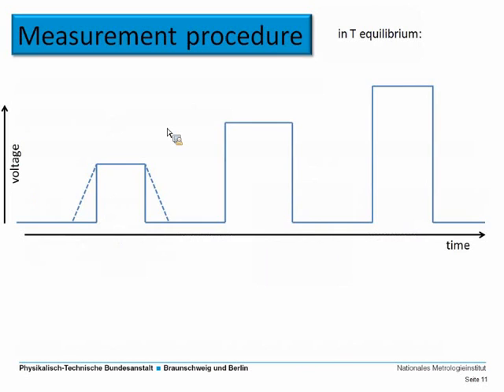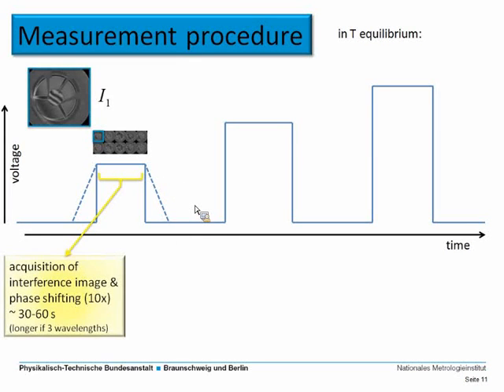Before I present the results, I want to say a few things about the measurement procedure, because although it sounds quite simple, it's actually not really simple. So once our system has reached some temperature equilibrium, whether at room temperature or higher temperature doesn't matter, once it's in thermal equilibrium, then at first we have the voltage off, then we switch it on or ramp it up to some initial value, leave it on for some time, then ramp it down again, wait for some time, go to the next higher value, switch off again, go to the next higher value, and so on. And we do something while the voltage is switched on, and we also do something while it is switched off. While it's on, we acquire the interference images.